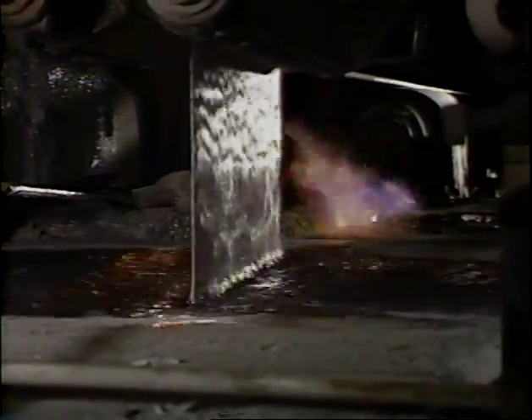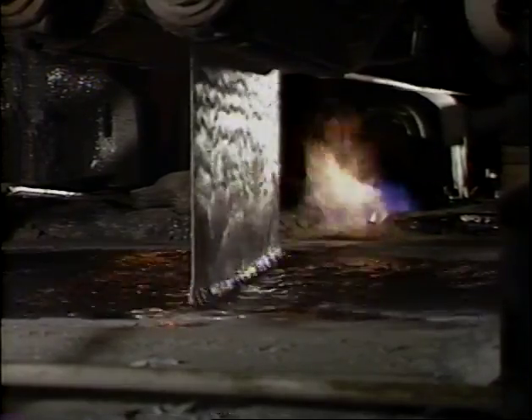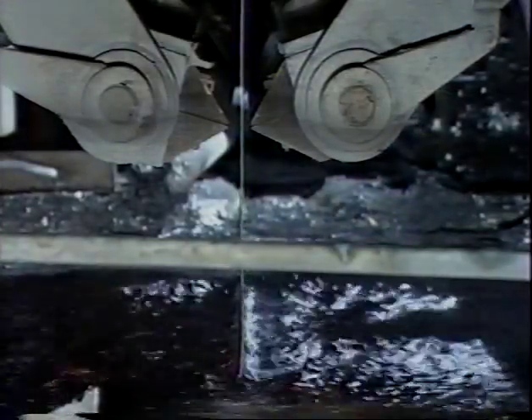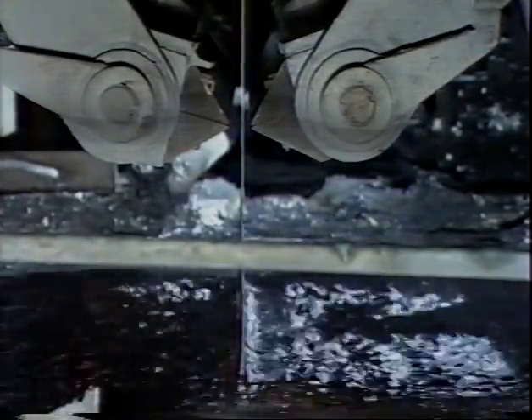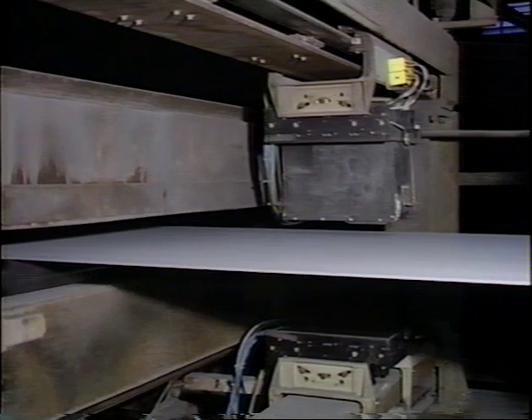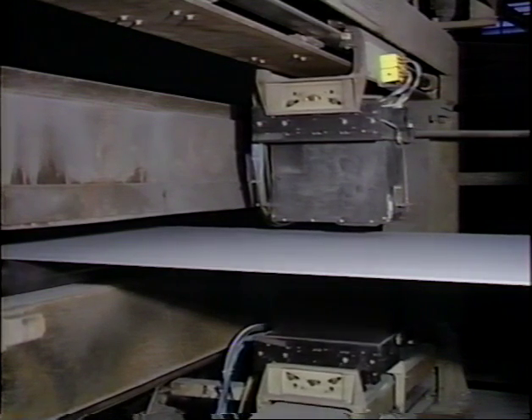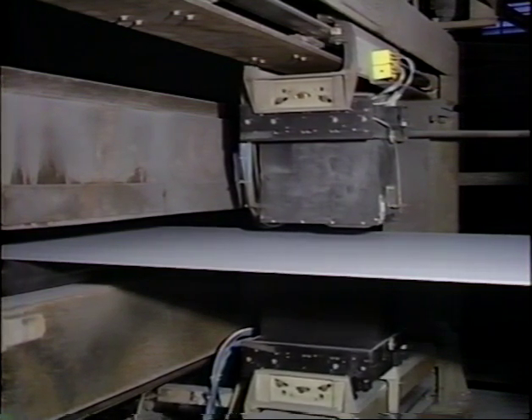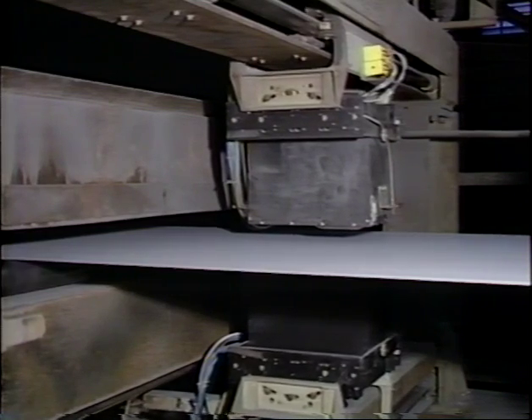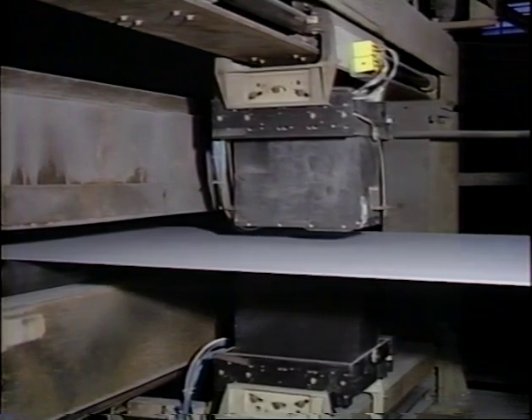Finally, the strip gets its corrosion-resistant coating in the molten zinc pot. As it emerges from the pot, the coated steel passes between air wiping dies that are computer-controlled by a state-of-the-art scanning X-ray gauge. The wiping dies and scanning gauge ensure that the customer's specified coating weight is met, edge to edge and front to back, consistently and uniformly.